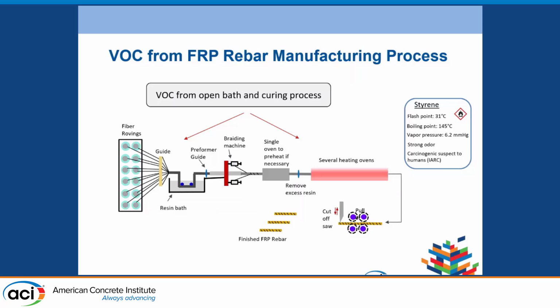For vinyl ester or unsaturated polyester, we typically use styrene as a reactive diluent. Styrene has some EHS concerns. It has a low flash point, so it is flammable. It has a low boiling point and high vapor pressure. Styrene also has a very strong odor. Also, styrene is considered a suspected carcinogen to humans by the International Agency for Research on Cancer. The VOC is mainly from the resin bath and the curing process. For epoxy systems, because we don't use styrene, we don't have this kind of VOC issue.